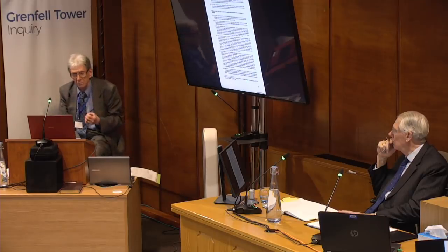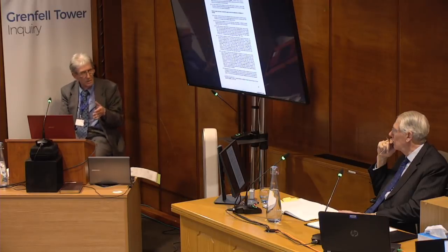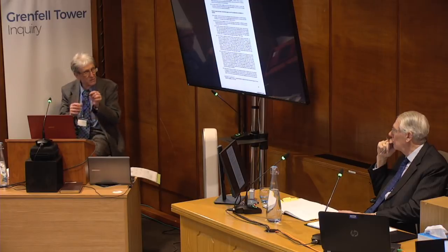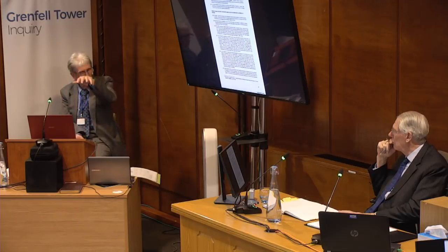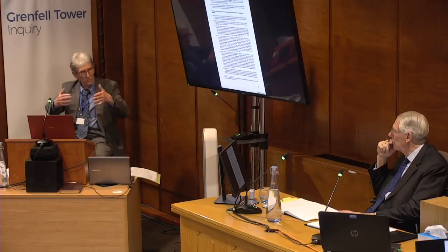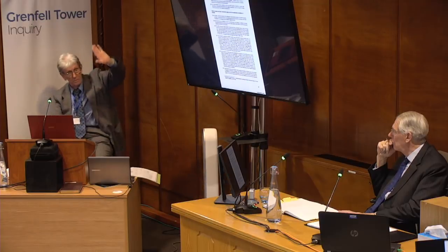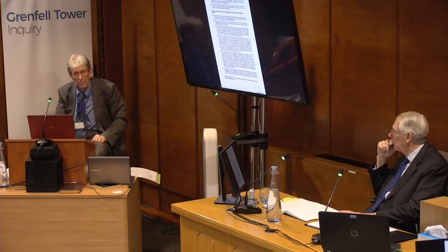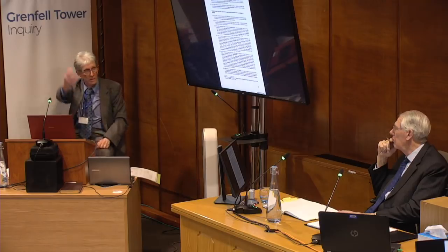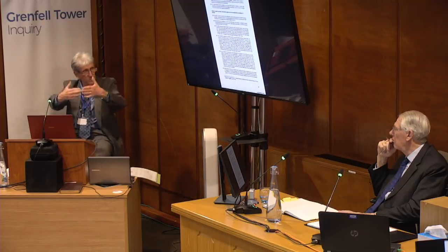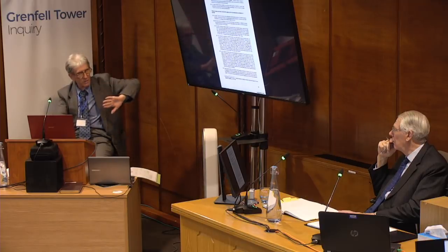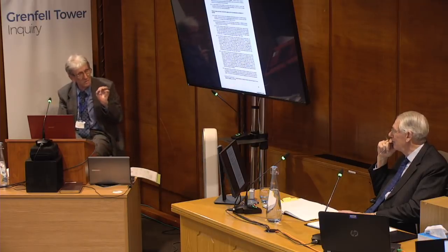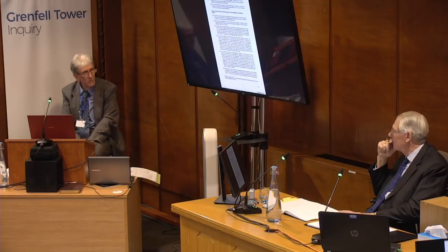So we did some experiments, we sawed up PIR and made it into cribs and ignited it, and it burned quite fiercely under those artificial conditions. We calibrated that to get the right heat output and then put it into this ISO room, which is now lined with PIR aluminium-faced panelling. And what happened in these experiments is that the standard size flame in the corner of this room never penetrated the aluminium and never involved the PIR. So in that particular case, it performed very well.